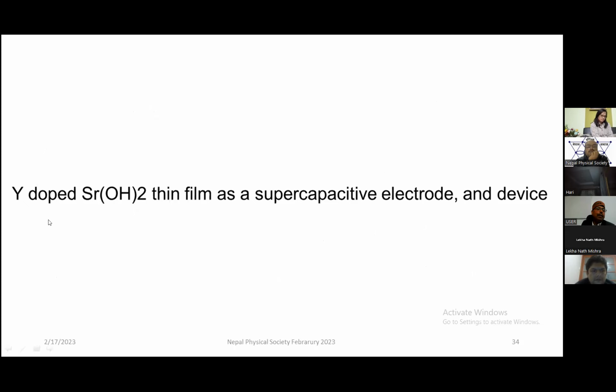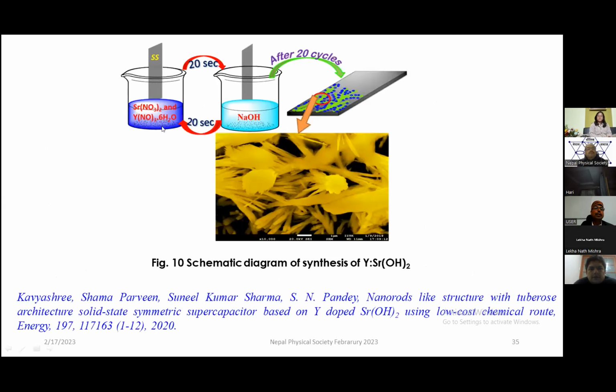So for that, the next part is the yttrium doped strontium hydroxide thin film as a supercapacitor electrode. This is the supercapacitor electrode. The aim is to increase the specific capacity of the supercapacitor, so the same method has to be used. The precursors we have taken are strontium nitrate and yttrium nitrate. We have optimized it for 20 seconds with the same SILAR method, and NaOH is here. With the help of this, we can make the yttrium doped strontium hydroxide thin film.